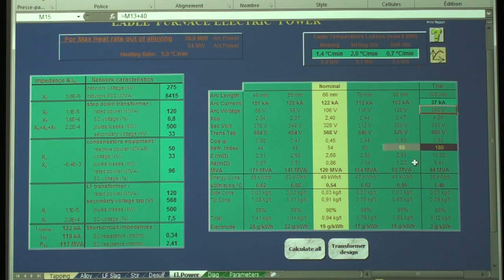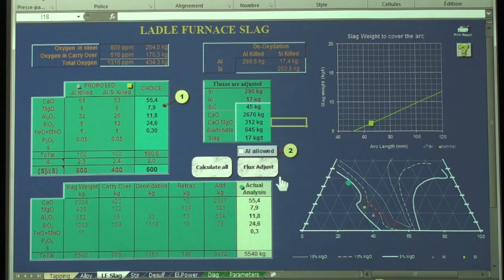Okay, I see. Wait, this 120 MVA is coming from here, because the criterion I'm using is to keep the refractory index below 60. So you see different scenarios here. My favorite is, let's say, this one given by the slag thickness. Slag thickness, I have 17 kg per ton.